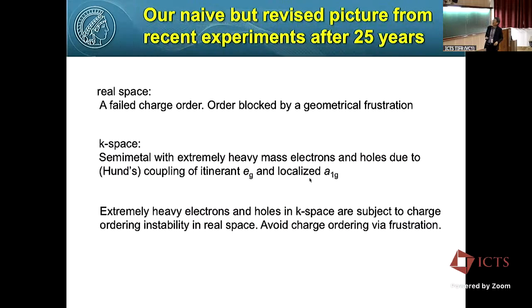That was in my mind for a long time, and I occasionally revisited this compound. Recently I revisited it again, and I believe I came to some conclusion. In real space, we could show the system is a failed charge order insulator, and all that is blocked by geometrical frustration. And in k space, we realized that it is a semimetal with extremely heavy electrons and holes, very likely through Hund's coupling of itinerant eg and localized a1g. Of course, these holes and electrons are subject to charge ordering instability in real space, but because of geometric frustration, they avoid ordering. That's my scenario for the heavy fermion state of this compound.